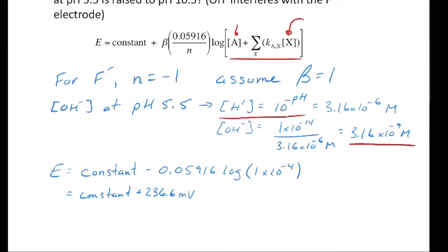So when we set up the equation to determine the voltage, we can just use this here, where everything after the log function is just the concentration of fluoride, and we end up with a constant plus 236.6 millivolts. Now the constant doesn't really matter, but it's going to be there anyway. What really matters is the 236.6, because when we determine the voltage at pH 10.5, we're still going to have that constant, but the constant is going to be the same, so all that really matters is the 236.6 millivolts.